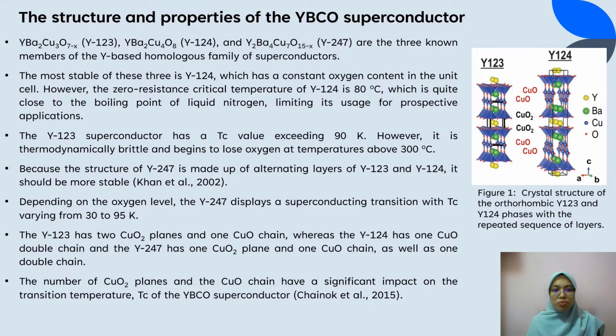The Y123 superconductor has a Tc value exceeding 90 Kelvin. However, it is thermodynamically brittle and begins to lose oxygen at temperatures above 300 degrees Celsius. Because of the structure, Y247 is made up of alternating layers of Y123 and Y124. It should be more stable. Depending on the oxygen level, the Y247 displays a superconducting transition with Tc varying from 30 to 95 Kelvin.